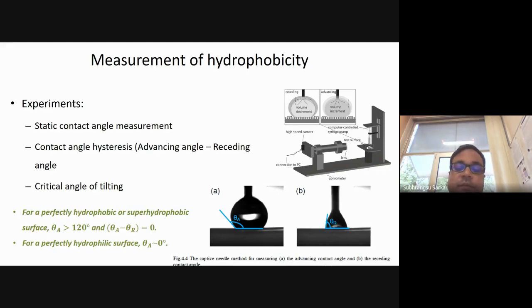Now there are two kinds of contact angle measurement. One is called static contact angle measurement, in which we just drop a little bit of water on the surface and we measure the contact angle that it creates. In figure A on the bottom panel, this theta A is the measure of a contact angle. Now, what is also important is that when you take the water out of the surface, to observe whether this contact angle remains the same or changes. For a perfectly hydrophobic or super hydrophobic sample with the contact angle above 120 degree, let's say, we expect the water droplet to not stick to the surface at all. And this contact angle should not change when we take out the water. Because if a material is hydrophobic, there is no reason why it would like to keep some water on top of it. It will just let go of it as soon as it's possible.